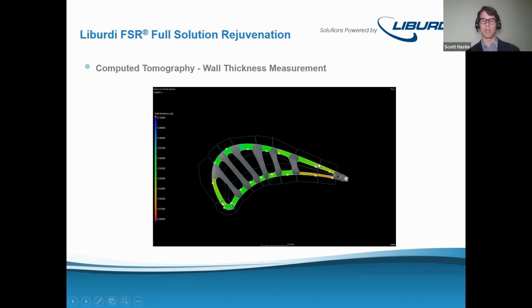So we're going to look within this section and this section and this section all the way around the turbine blade, and they'll likely have different limits as to the maximum and minimum condition in there. And then the software helps us to pick the minimum, and you can see the white dots around the internal and external surface. That's showing where the minimum ray from the external surface to the internal surface, or the internal surface to the external surface, gets the minimum wall thickness. And then we can compare that against the criteria, and most importantly, reject parts that shouldn't go back into the engine, but not call parts just because they've run 24,000 hours if they still meet the dimensional requirements.